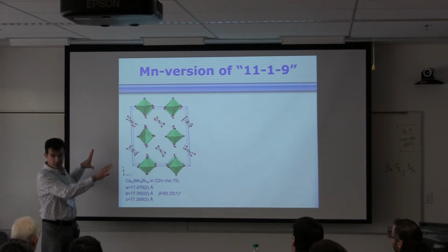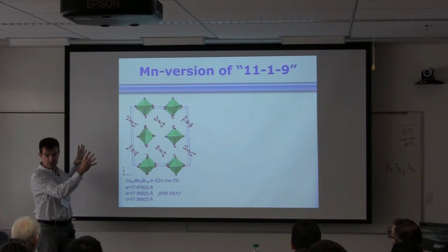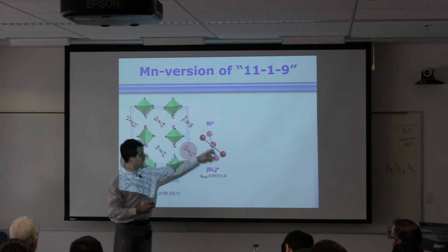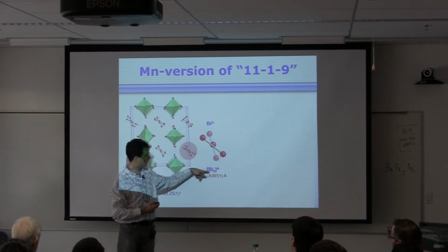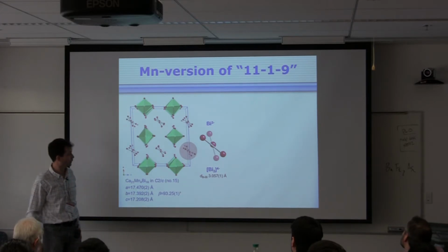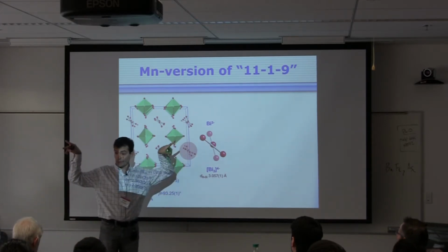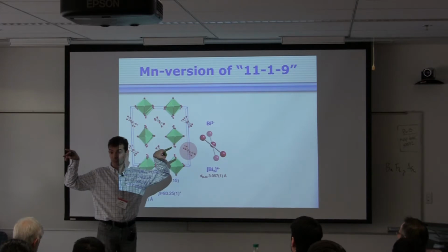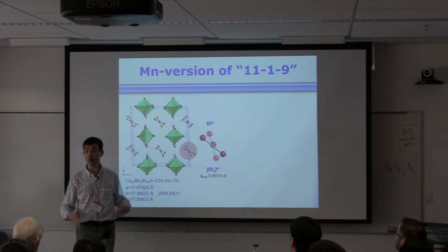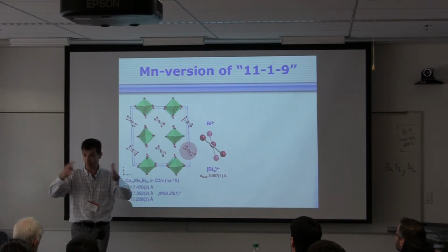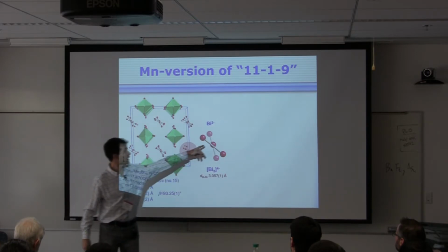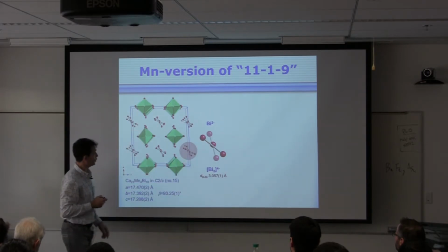Now this is the monoclinic unit cell projected without the calciums. Breaking it up, again we have dumbbells. Now this is bismuth. Again, the bismuth and antimony are just one above the other. Bismuth in the metal is 3.6, in this compound is 3.06. This is over a 20% reduction in the separation between bismuths upon adding electrons. Extra bismuth, which is just in an octahedral hole.